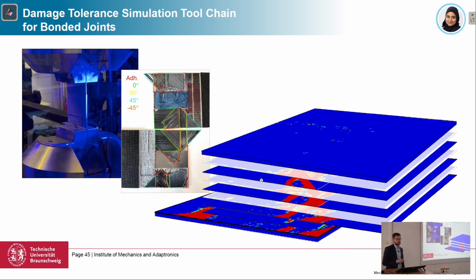We are responsible for the residual strength simulation, and we performed some validation experiments. Here's a UTM, universal testing machine, with again a single overlap joint, but a bit wider than a standard coupon, so 100 millimeter in width here. And we inserted a release film to have an artificial damage in the structure, and then performed the test and saw a very complex damage pattern through all the layers, or up to the first 0 degree layer.